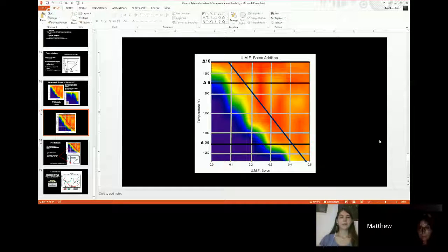Well, the whole catch is, and I will fill you in, because Kristen saw my talk at NCECA this year, was talking about applying this same concept to cone 04. Basically the same research that I did here at cone 6 with the dishwasher, I then took all the way down to cone 04. The short version of the results is the flux ratio, that 0.3 to 0.7, is the big deal as far as food safety. As soon as you begin to expand, especially your alkaline metal content, so your lithium, sodium, or potassium,